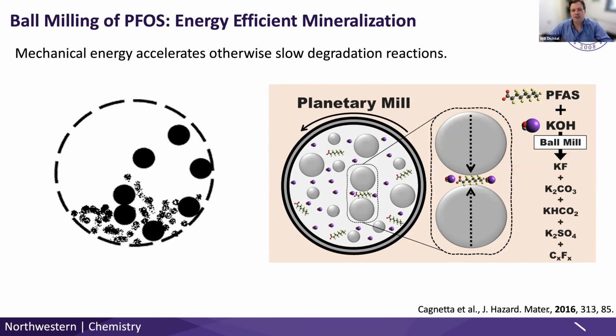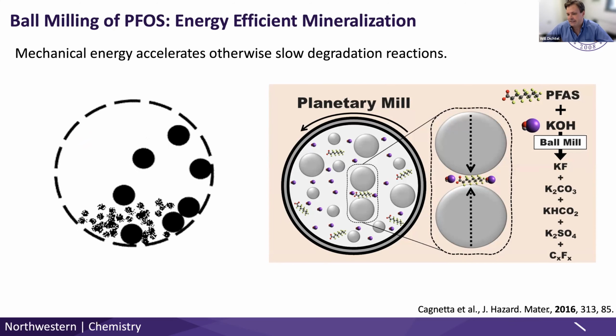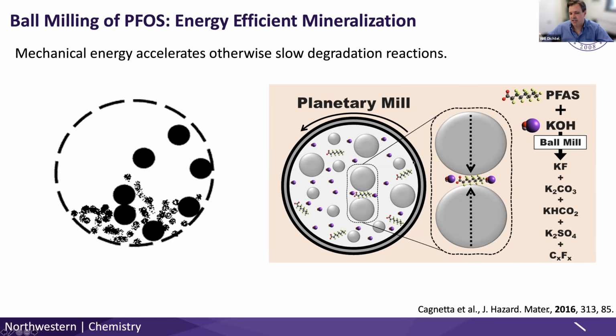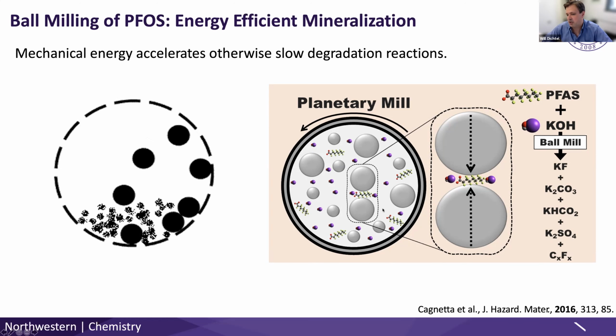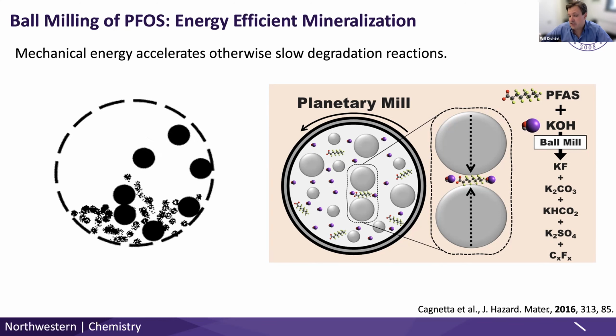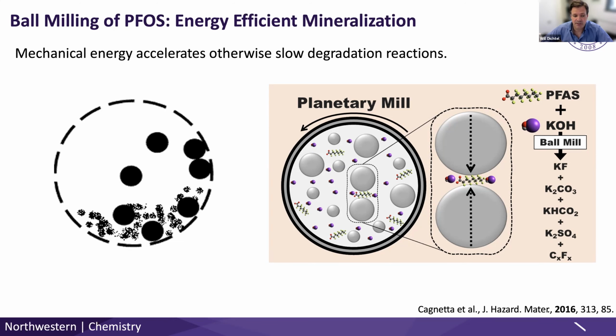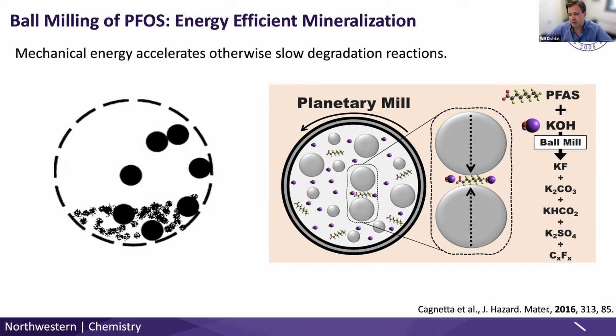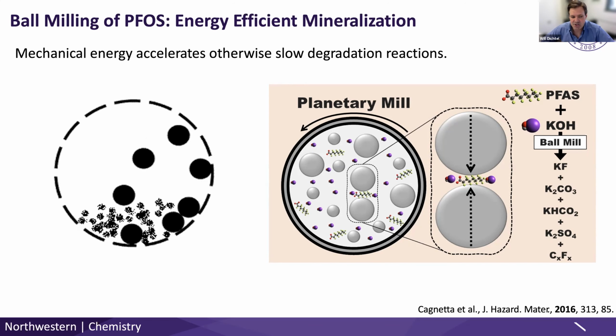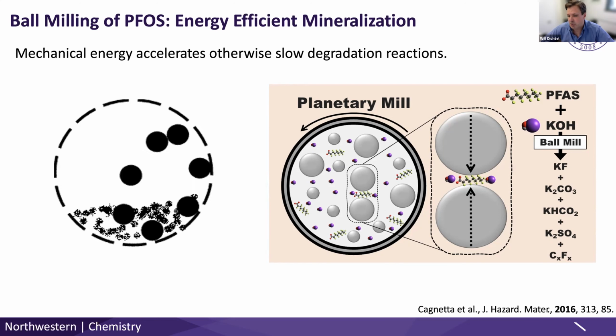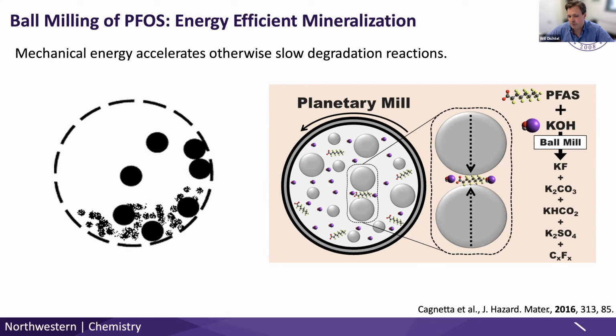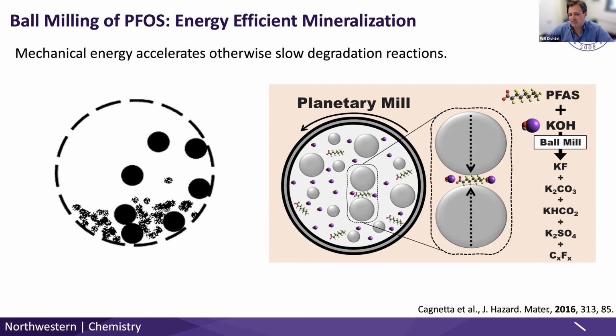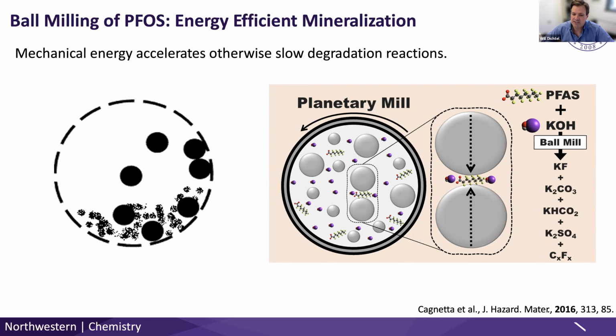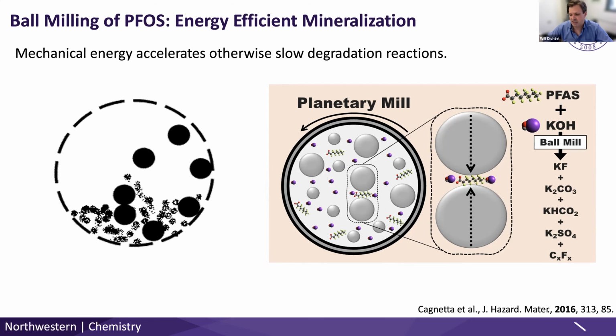It's using a technique called ball milling. The idea here is that you take your PFAS coming off your adsorbent, and one way to destroy it is actually to apply mechanical energy. You literally agitate it with these steel ball bearings, and put just tons and tons of energy, which is actually enough to break down these materials at the molecular level.